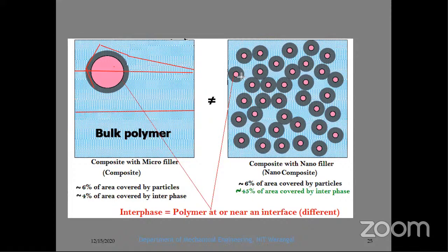If you see in these particular composites, if a crack is initiated here, it will come and stop here. As earlier, it may take a deviation or it may pass through it. Again, when it comes to this particle, it will stop for a certain time and again take a deviation. Again it will come here, stop and deviate or pass through it. So before reaching this point, almost 5 times the crack is stopped and takes a deviation. So you can imagine the lifetime of that particular material will be increased when you have nanomaterials.